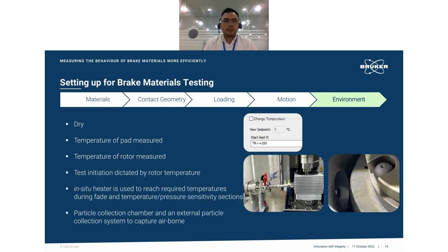In terms of environment, for this test it is dry. We don't mimic any on-the-road conditions such as water, mud, etc. But at the same time, we do measure the temperature of the brake pad and the temperature of the rotor disc. And the test initiation, as required by the AK Master, is dictated by the rotor temperature. The test will start when the rotor disc achieves a certain temperature.